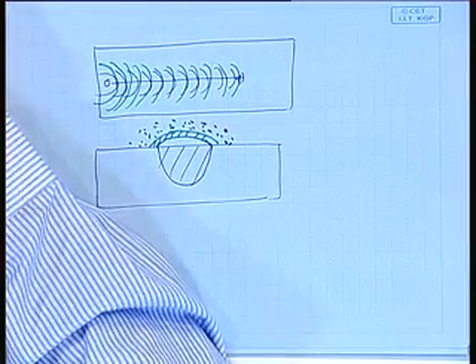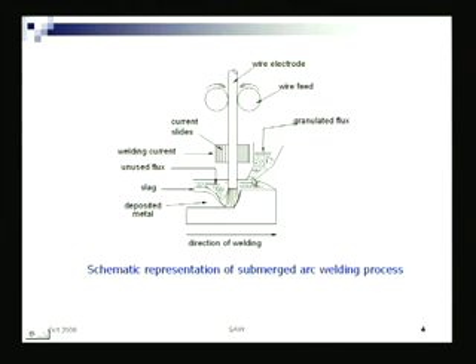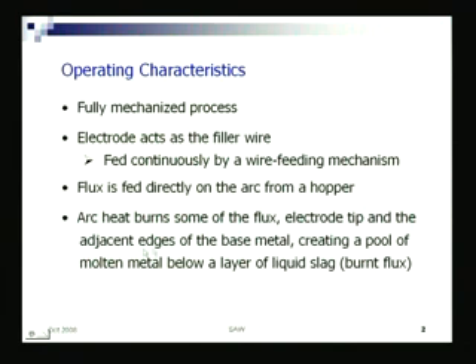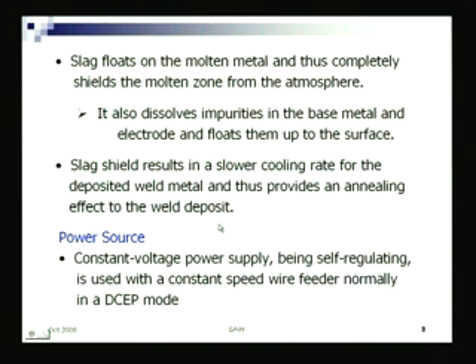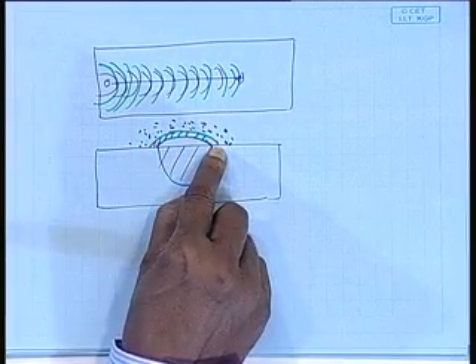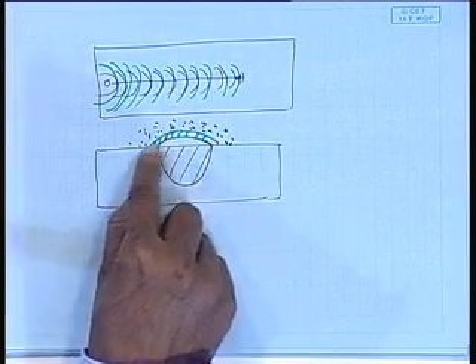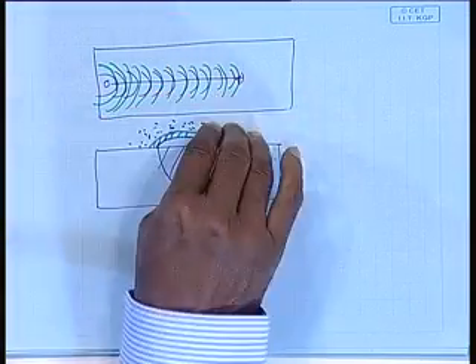Because as you see, this is continuously being fed, those granules of flux, and now some flux is burnt, not the entire amount. A part of it will burn and form the slag. That slag will float up above the molten metal and form a solid crust, shielded with unburnt, unused flux. Later you can recycle it.